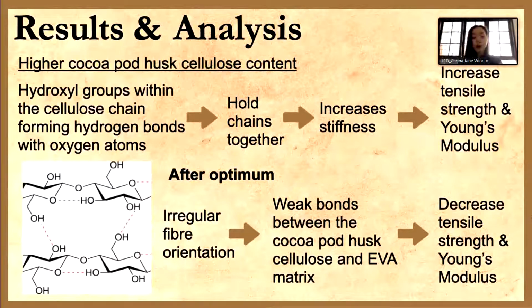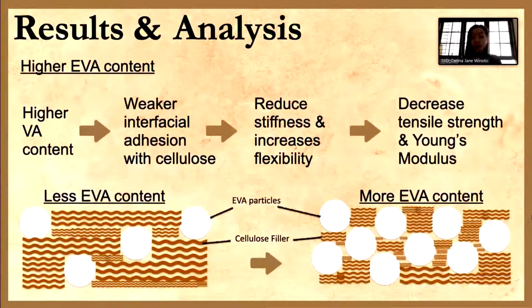However, after the optimum point predetermined as sample D, irregular fiber orientation occurs, weakening bonds within the cocoa pod husk cellulose and EVA matrix, decreasing tensile strength and also its Young's modulus. For EVA content, it can be said that higher vinyl acetate composition causes weaker interfacial adhesion with the cellulose fillers, reducing stiffness, thus increasing flexibility, and also decreasing tensile strength and Young's modulus.